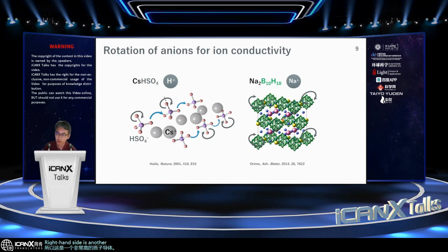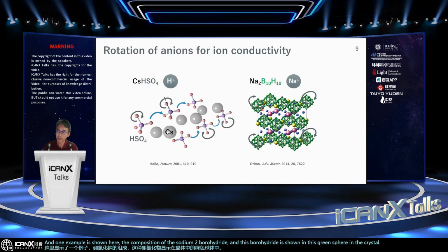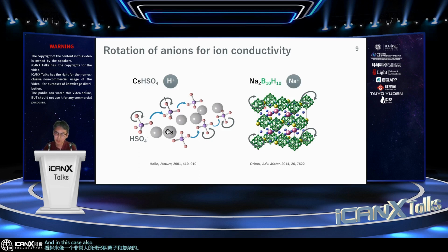The right-hand side is another ion conductor, a sodium ion conductor, which is also very important for sodium batteries. One example shown here is a composition of sodium-2 borohydride. The borohydride is shown as the green sphere in the crystal structure. It looks like a very big, spherical complex anion. In this case, as the temperature increases, the borohydride anion starts to rotate. Because of the cooperative rotation, the intercalated sodium ion starts to migrate very fast. So this suggests that even in a solid state, if we can control the rotating properties, we can aim to get ion conductivity in the solid state.